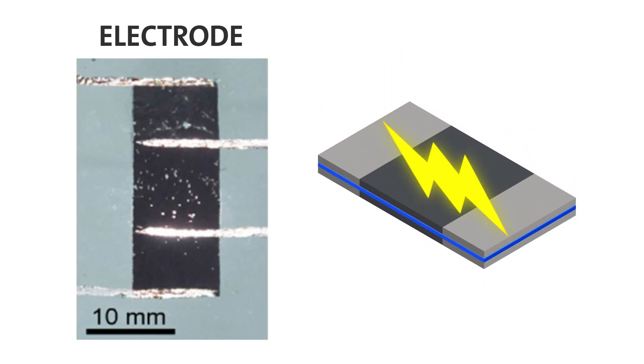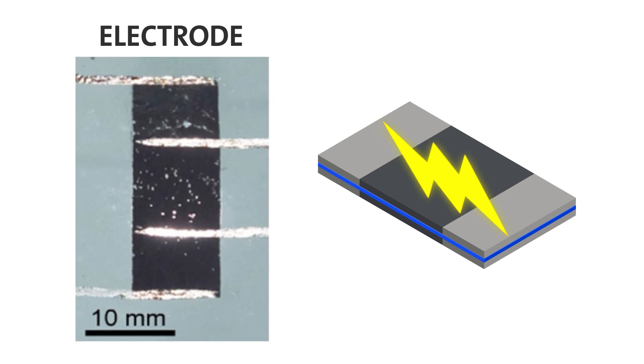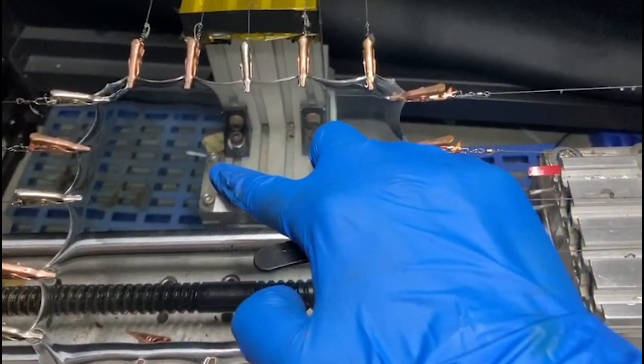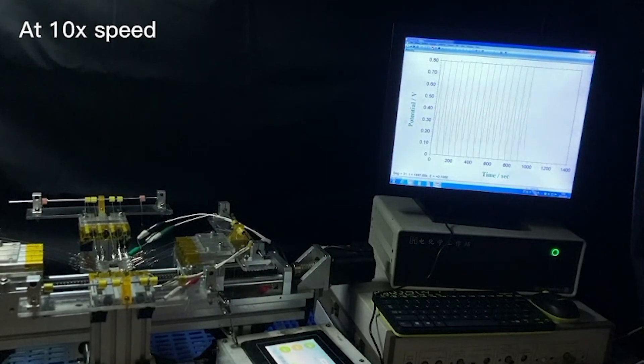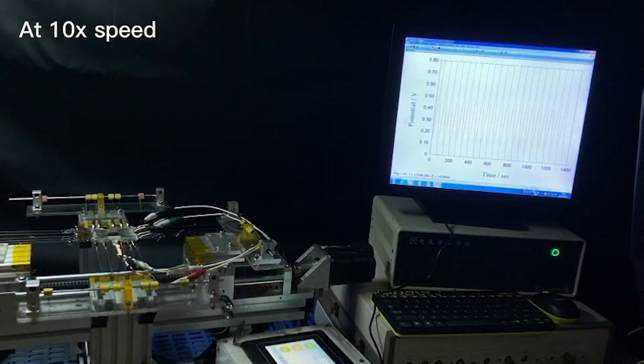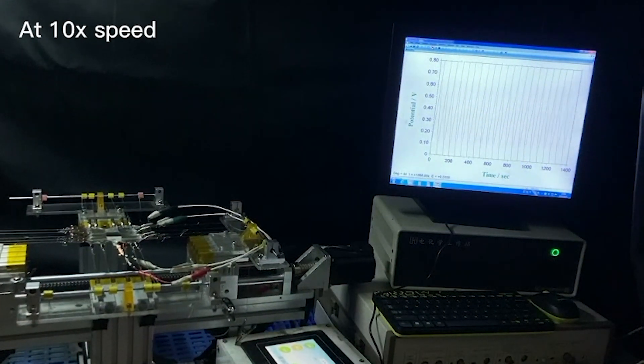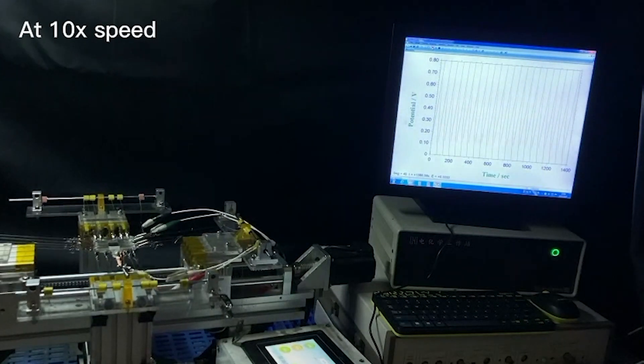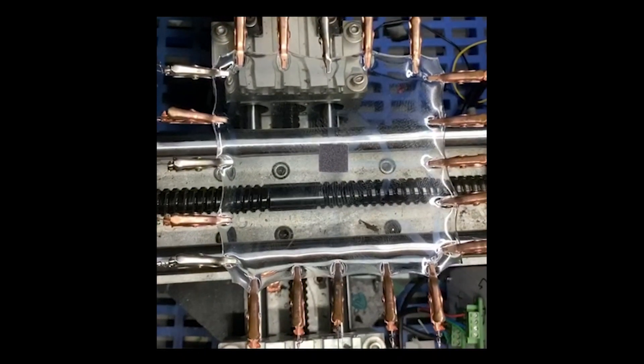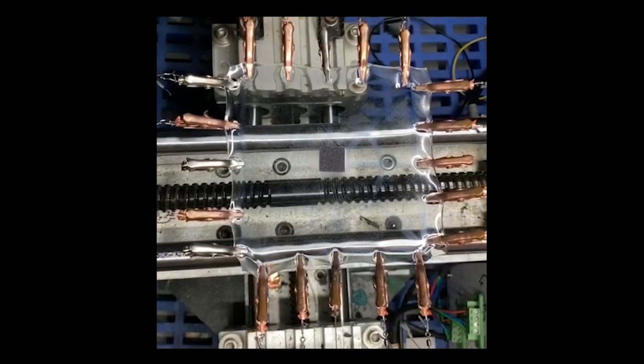The device had a high energy capacity similar to other metal carbide supercapacitors, but its advantage was that it could be stretched out to 800% its initial size without cracking, and it could be recharged to approximately 90% of its initial storage capacity after being stretched 1,000 times and after being bent or twisted. The researchers say their stretchable supercapacitor has excellent energy storage performance and is an attractive option for powering future wearable electronics.